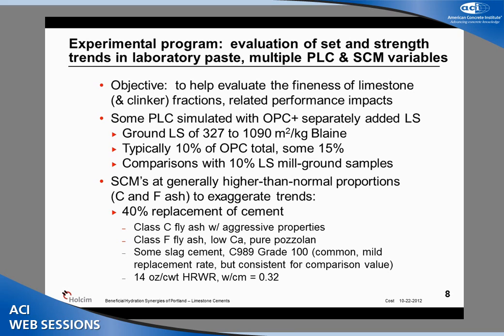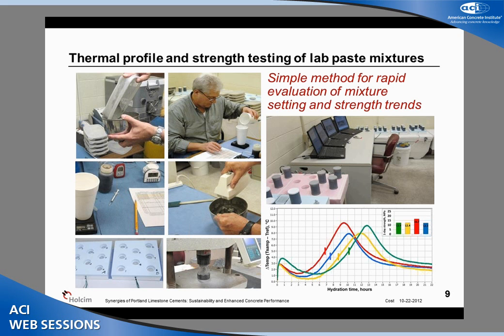We conducted some initial experiments with laboratory paste to see if we could better understand this. And since the ability to characterize a ground system as far as the distinctive particle size properties of the limestone as it differs from the clinker is very difficult to do, we decided, in the laboratory environment, to simulate Portland limestone cement with separate ground limestone additions to ordinary Portland cements. And we did this also in comparison to mill ground Portland limestone cements. And we used some SCM replacement rates that were a little bit higher than norm to kind of exaggerate the trends that we were interested in paste mixtures.